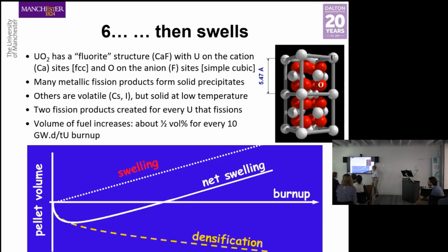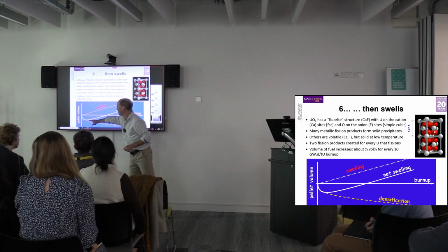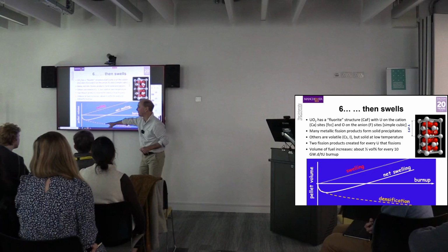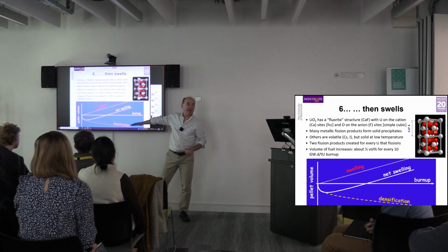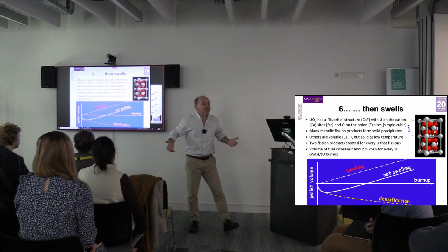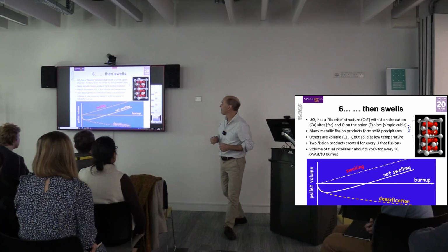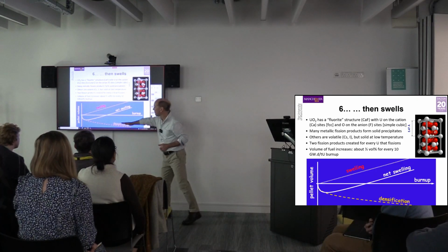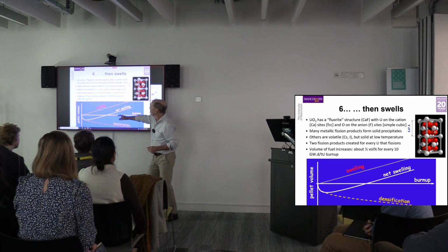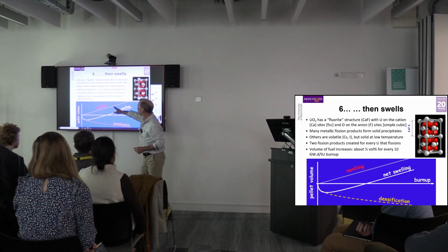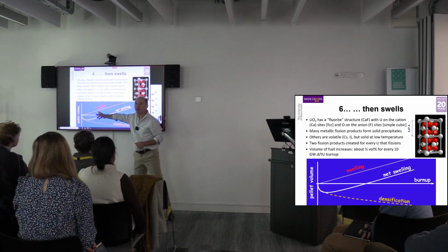Yeah, so we started at 5%, and then we get down to 4.5, 4, 3.5, 3, 2.5. Well, eventually, the pellet's fully dense. We can't sinter anymore. We've already sintered out all of the porosity. So densification stops at some point in time. But this other line, this one that carries on monotonically going upwards, is swelling.